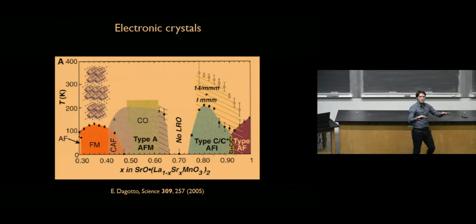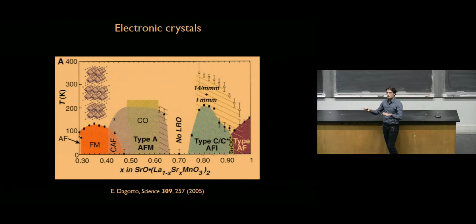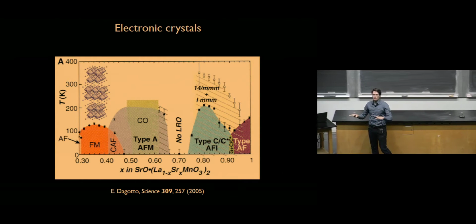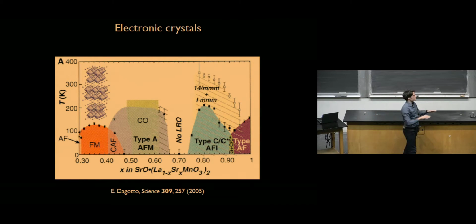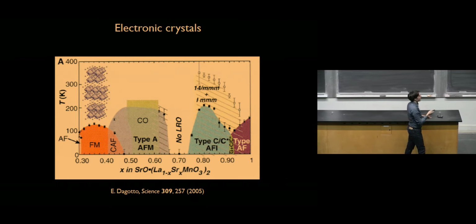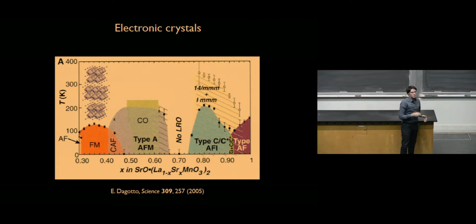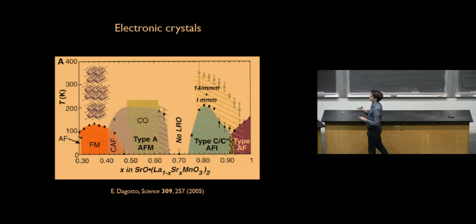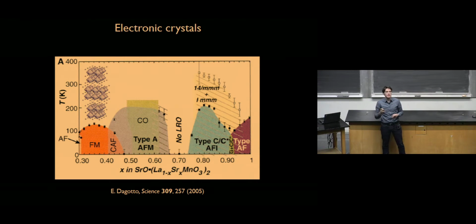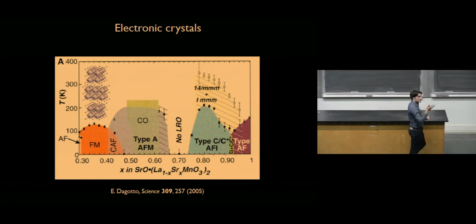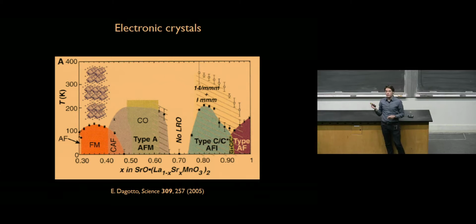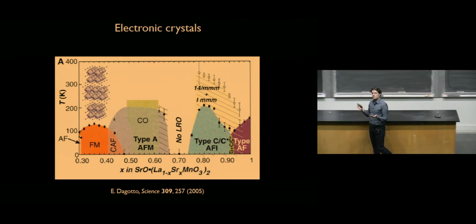You have a lot of possible electronic orders in your material that are waiting to be stabilized somehow by your choice of parameter. And as you browse around in this phase diagram, you can find all sorts of different phenomena happening. So it's a very delicate balance, but it's also a very powerful one, because that means that with certain types of experimental parameter, you can control the quantum state of your material, and this has very important implications for devices, for instance.